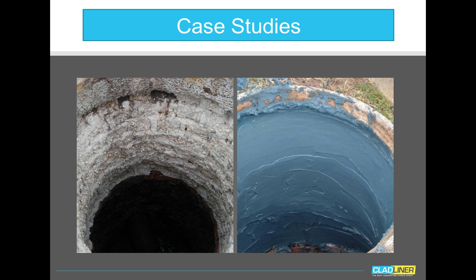That resurfacing mortar is very similar to a mortar that we use, or was actually the product that was used, was Clad Restore. It was sprayed on using a wet spray method, or gunite spray. About an hour later, the Restore was firm to the touch, and at that point, the Cladliner, using the same spraying equipment, was able to be spray applied and back troweled over the resurfacing mortar.